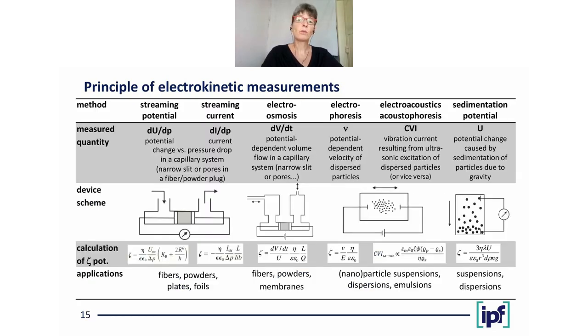On this slide, the most important electrokinetic methods are summarized. I don't want to explain everything in detail. I just want to tell you for different sample geometries, like for instance fibers, powders, plates, or foils, or particle dispersions, suspensions, there is a method that enables us to measure the Zeta potential, and there is an equation that allows us to derive the Zeta potential from measurable quantities.